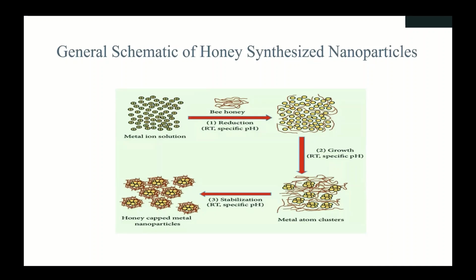We get the metal ions, put them into a solution. We add the honey, and then during the process of stirring and heating, the nanoparticles form, and they do the capping and the reducing of the nanoparticles. And so now at the last, on the lower left-hand side, we see the nanoparticles that have been synthesized using the honey and the silver nitrate solution. Next slide.